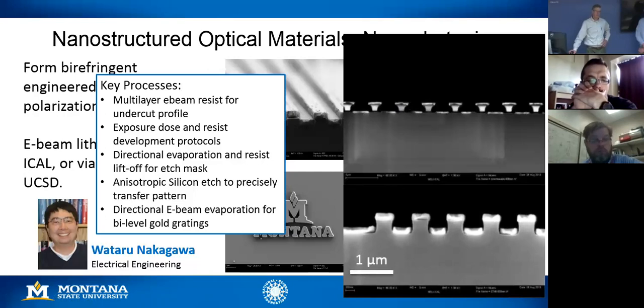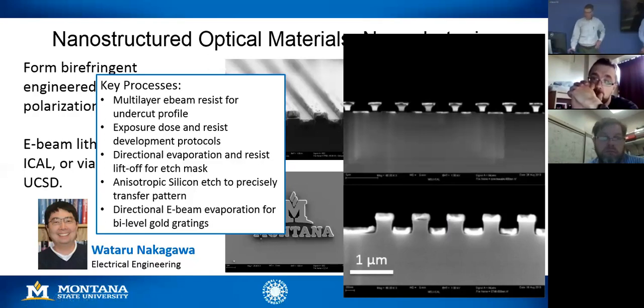You can see the scale bar here, 1 micron. So this is nanoscale etching in the silicon. And once again, for these structures, they need this undercut profile on the etched features because they're going to once again deposit a very specific layer of gold on the surface of the silicon to build this unique nanostructured optical device. So this is silicon. It's a bilayer grating of 2 different layers of the grating spatially separated in Z, and this gives the desired optical properties of those films.